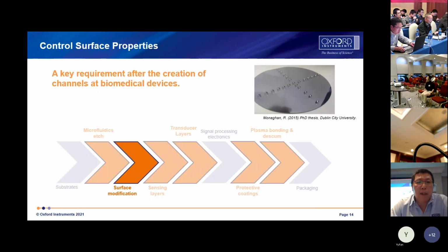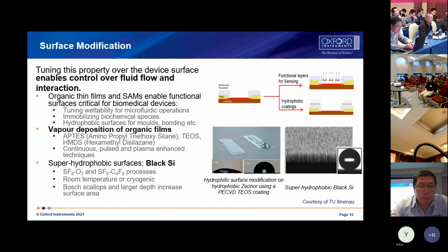Controlling surface properties is a key requirement after the creation of channels in biomedical devices. So about surface modifications: for example, a silicon substrate with silicon dioxide on top is a hydrophilic surface, while a PMMA surface is hydrophobic. Tuning this property over the device surface enables control over fluid flow and interaction.